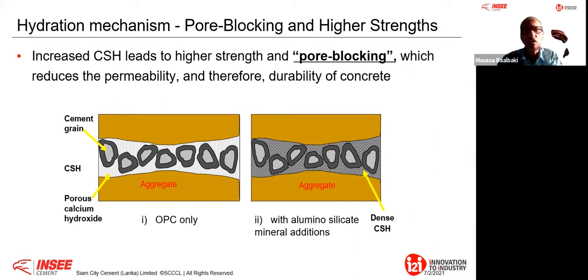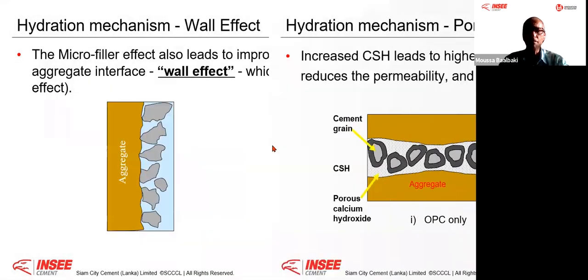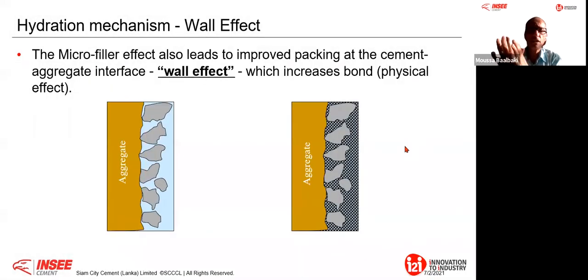Now, if I mitigate this Portlandite, I add the silicate or aluminosilicate material in the Portland composite cement, I can densify it by forming more calcium silicate hydrate. And suddenly, thanks to the aluminosilicate constituent that you put in your Portland composite cement, you can further improve the durability of your concrete.